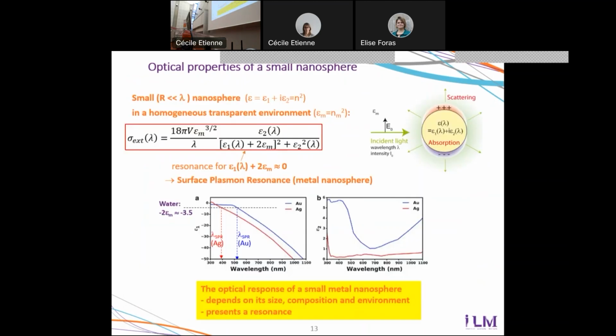So then these cross-sections are quite difficult to estimate for complex nanoparticles, but they can be analytically computed in a few simple cases. And one of the simple cases is that of a small nanosphere, so small in the sense that its radius or diameter is much smaller than the wavelength of light, standing in a homogeneous medium. So the same medium all around the sphere. So in this case, there is an analytical expression for the extinction cross-section. So how much the particle absorbs and scatters light.